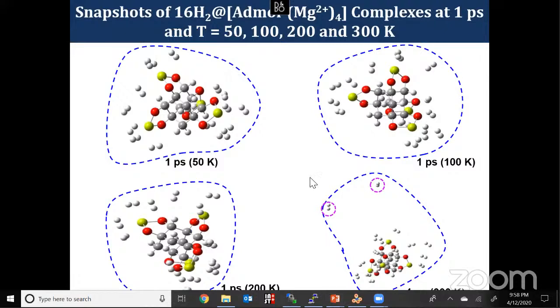So these are the snapshots I'm sharing. At 50 Kelvin, there is no desorption taking place, as well as at 100 and 200. So up to 200 Kelvin, the molecule is not ready to release hydrogen molecules. But at 300 Kelvin, 1 picosecond, the moiety is releasing 2 hydrogen molecules. If you increase the time, obviously the molecule will release more hydrogen molecules.